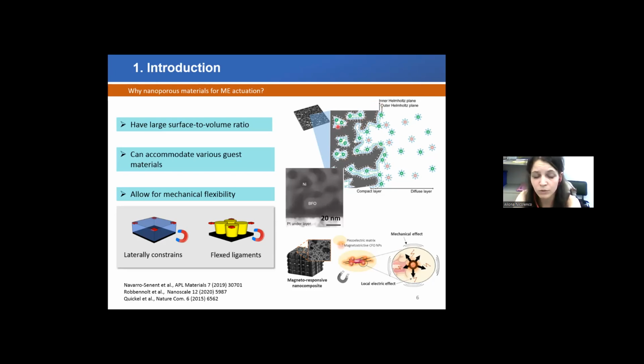Then the nanopores can also accommodate various guest materials. This is another example. Here we have a mesoporous bismuth ferrite matrix that is filled with nickel by electrodeposition. Nickel, by the way, is also a magnetostrictive material, even though its magnetostriction is much less than for iron gallium. But in this way, another kind of magnetoelectric composite can be prepared.